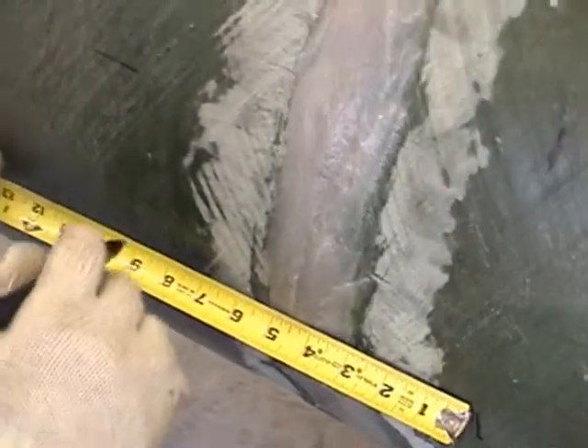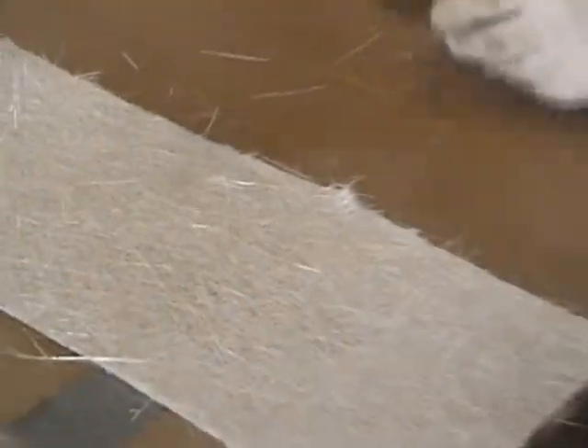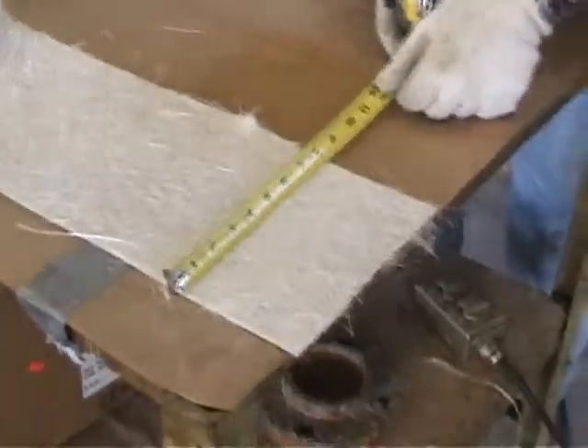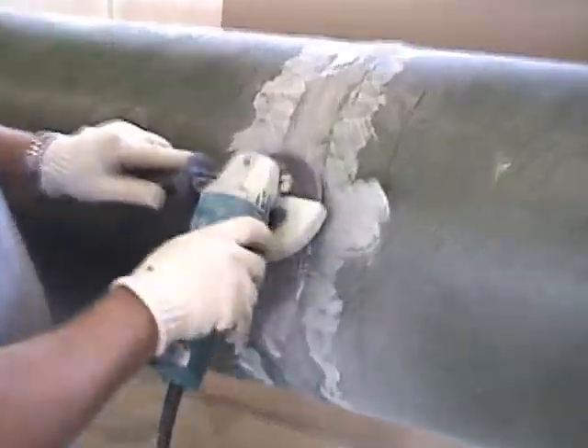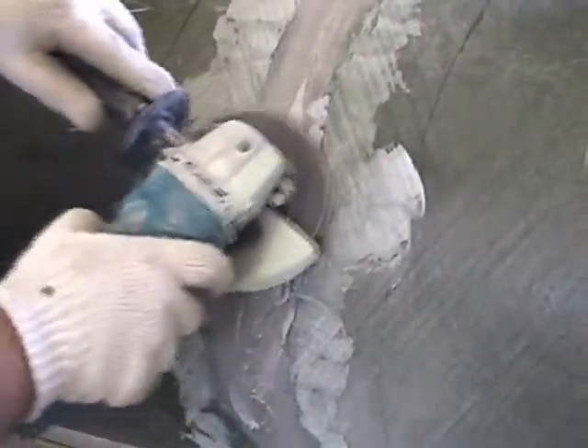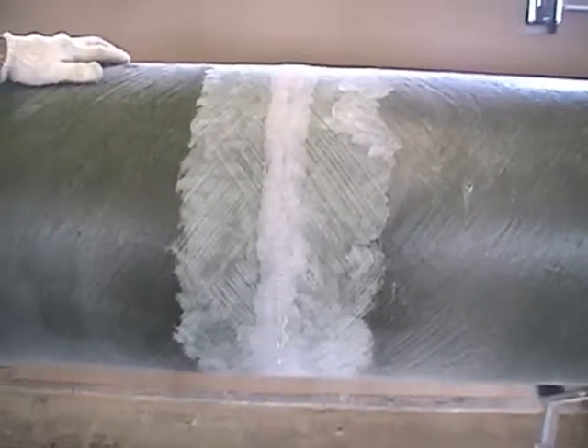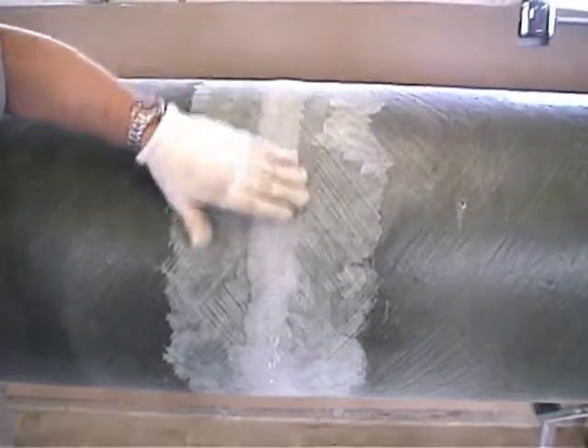The width will vary according to the pipe size and pressure rating. That's why it's important that you unwrap your glass and measure the widest piece of glass, which is your cover mat, which will fluctuate. Now that the adhesive is cooled down and we have the area marked for the widest piece of glass, we will use the grinder to shape the adhesive by taking the highest point out and feathering the edges down. Now that we have the adhesive ground down and feathered on the edges, and we now have our widths, we're ready to apply the glass and resin.